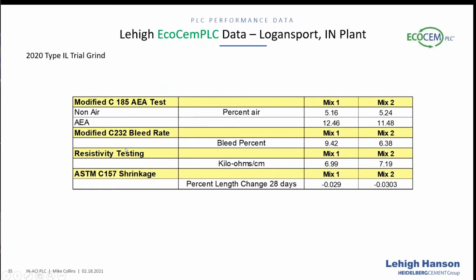Something that has been significant, and again makes sense if we stop and think about it, is when we run the C232 bleed rate test, we're looking at a bleed percentage on a given mix. The Logansport Type 1 bleeds 9.42%. The PLC mix, again because it's ground finer, has less bleed, about 3% less, 6.38%. This is something that we have found to be beneficial in a couple of different applications, and it's something we've seen repeated from plant to plant to plant as we've looked at our different production cements.